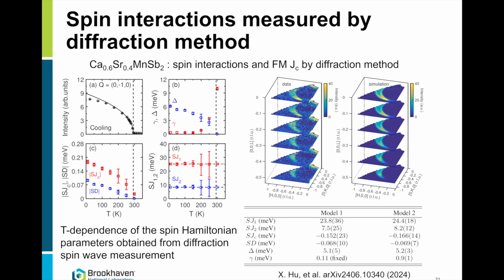All right, so we can easily fit this to a one-dimensionally projected spin wave and refine all the parameters of the Hamiltonian. Actually, as I say, in 2 days, it was an accidental measurement. We just had a weekend where we weren't able to change the sample, and so we carefully measured this sample, and we were able to measure temperature dependence of the spin gap. Here is the spin gap at many temperatures. This is the order parameter. Spin gap sort of tracks the order parameter.